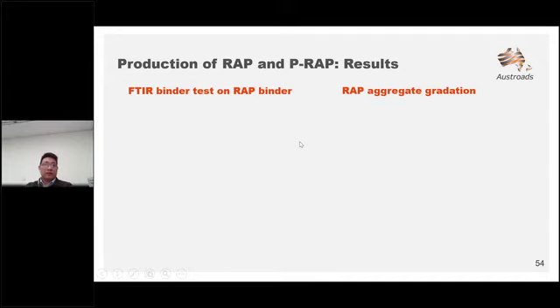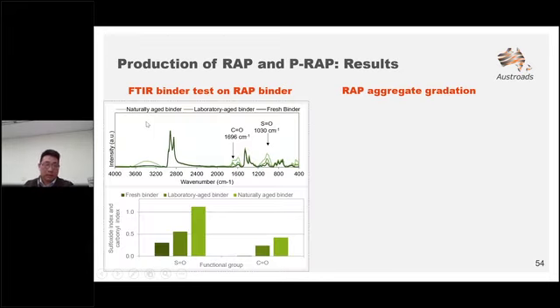So the lab produced RAP was checked for its extracted binder and the gradation. As we can see here from the FTIR binder test on RAP, it shows the jump in the peaks of carbonyl and sulfoxide of the RAP binder compared to the neat binder. And looking at the carbonyl and sulfoxide index, we can see the significant increase of those indices compared to the neat binder. So this result indicates that substantial aging occurred in the RAP binder via the proposed aging protocol.